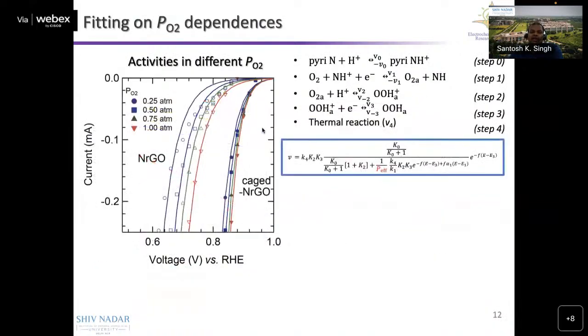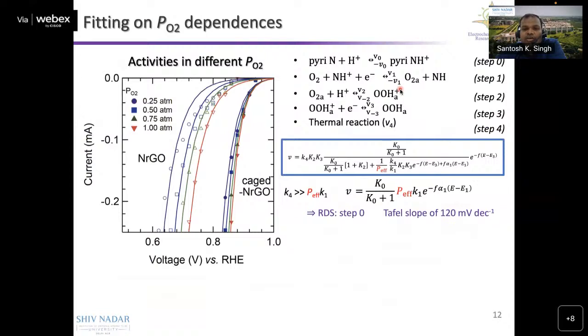Further, we have tried to illustrate the reaction steps of this catalyst. Here we can see the first step is the protonation of the pyridinic nitrogen, and the second is the oxygen adsorbing over the surface. Based on this Tafel analysis, we calculated the effective partial pressure of these gases in the hydrophilic and hydrophobic cases, and we found that the RDS for the hydrophilic case, which is 120 millivolt per decade, is following step 0. Step 0 is the rate determining step in this case. However, in the hydrophobic catalyst, which has 60 millivolt per decade, the RDS is the O2 adsorption over the surface and its reduction to OOH. So the third step is the RDS for this one.